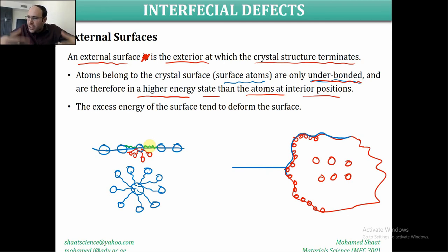So to compensate for this missing bonding force and to achieve a static equilibrium like any other atom inside the core, the bonding between all the atoms over the surface should be higher, to account for the missing one. That's why this would result in a higher energy, more bonding than the usual that we have for any regular atomic structure. So this is counted as a defect inside the material structure. It is good in some applications and bad in other applications, but we have to consider it.